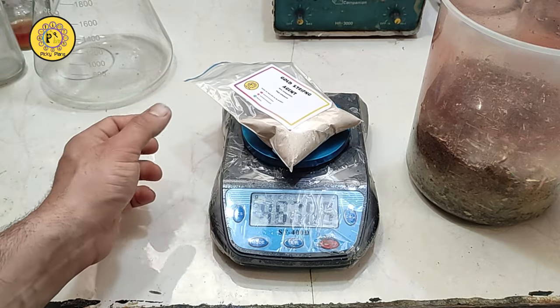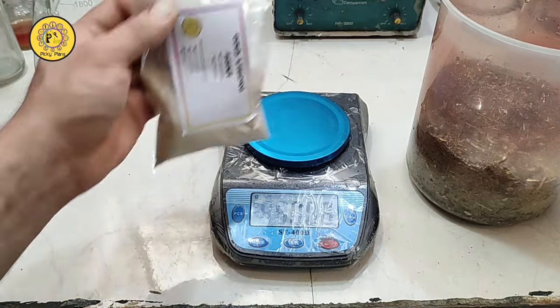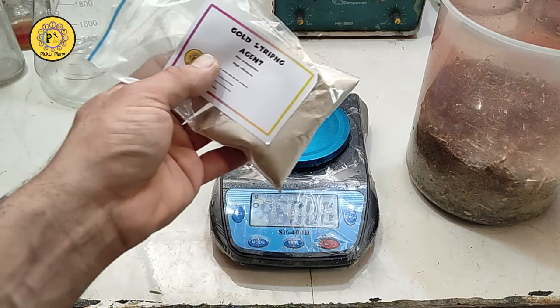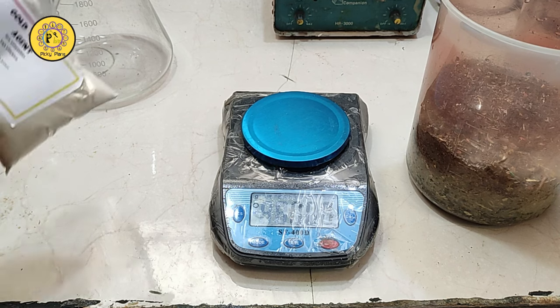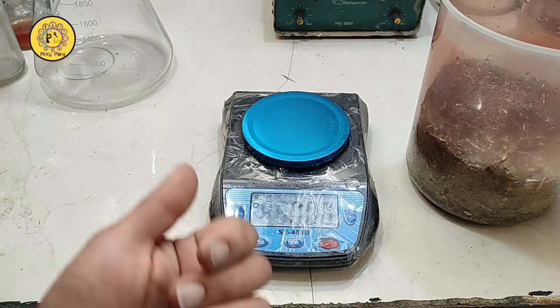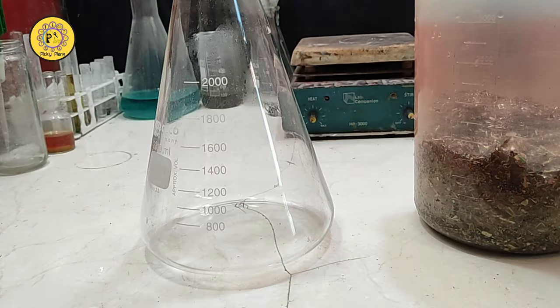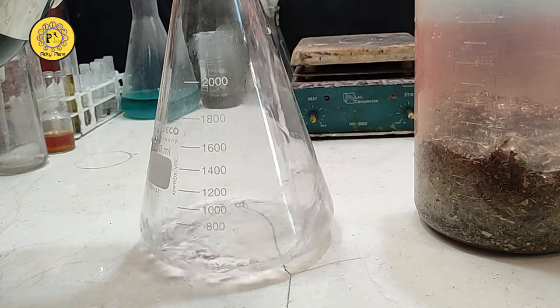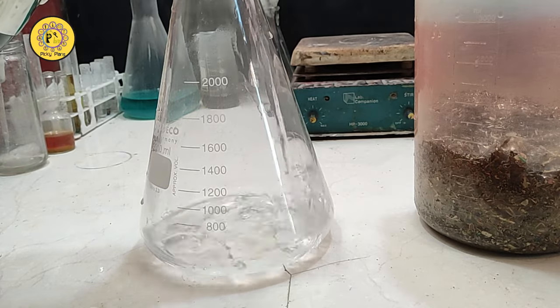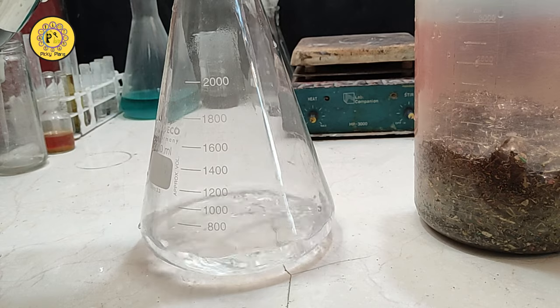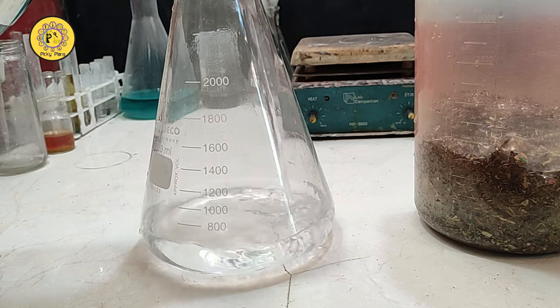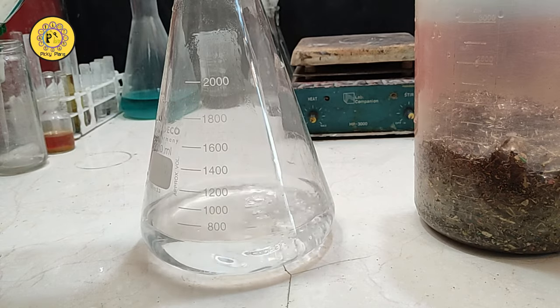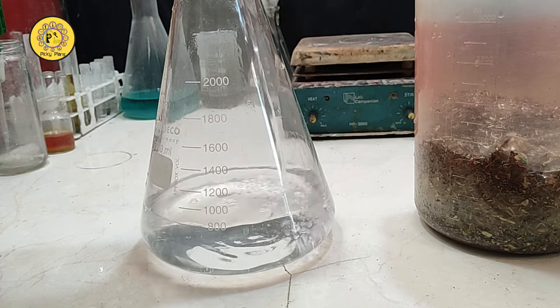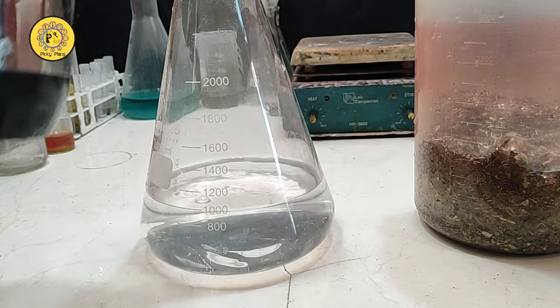Also, this is about 100 grams in the pack. I'm going to dissolve 100 grams of this powder in 1 liter. This is the sweet spot for this solution to work with. Right, to make our solution, I add 1 liter of water to this flask. This is hot tap water. You don't have to use distilled water for this purpose. Alright, 1 liter.